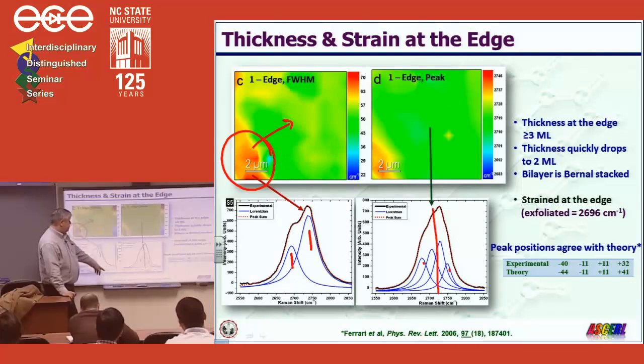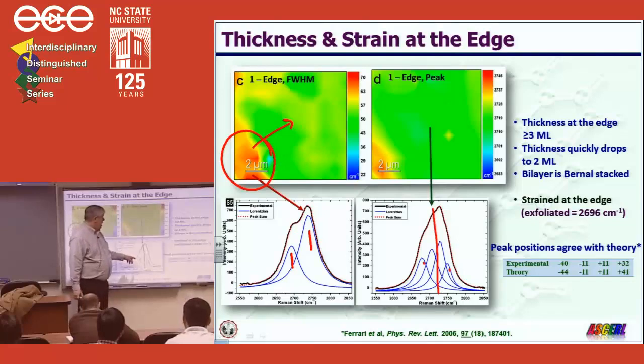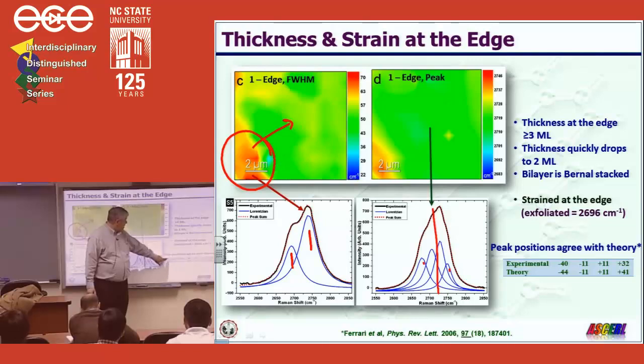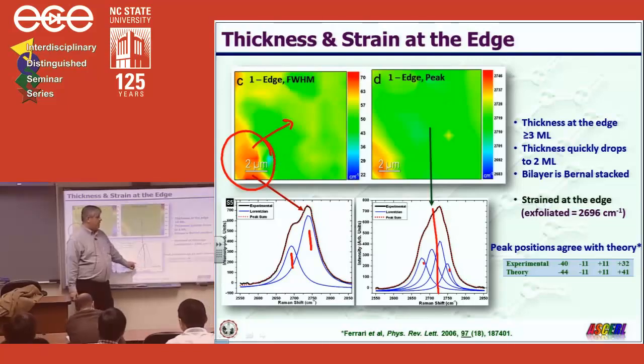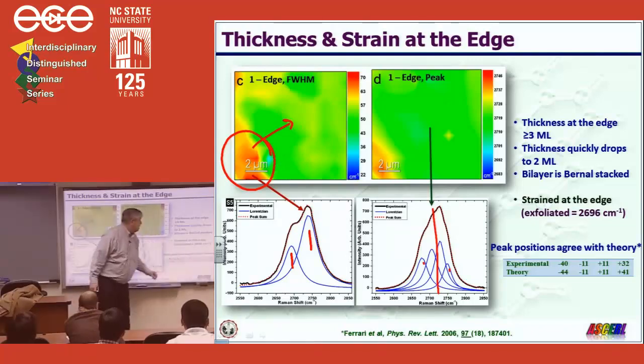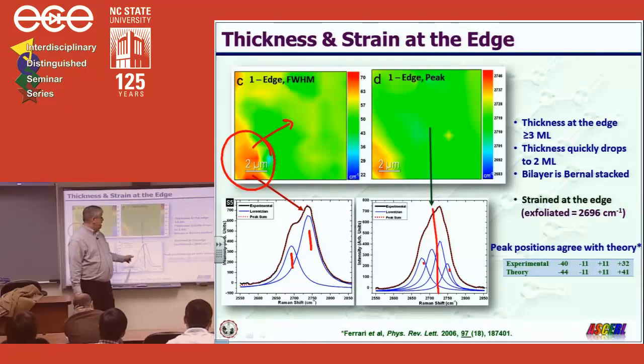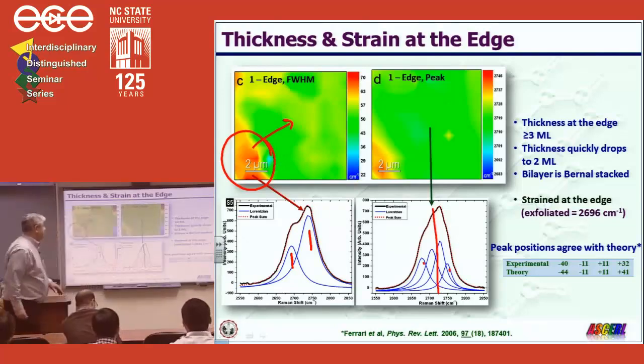Now, if you go to the original reference by Andrea Ferrari, he was the first guy who did this. There's a theory for where the peaks should be located. Okay. And here, this is our experiment compared to the theory of the position of the peaks. And you can see that they overlap relatively well. Yeah. Some deviation for the last one. We're talking about on the order of 9 wave numbers. Yeah. And considering the accuracy of the measurements about 2 wave numbers, that's pretty good. Yeah. And if you look at Andrea's paper, actually our fit's better than his. Yeah. So it's actually a very good fit.